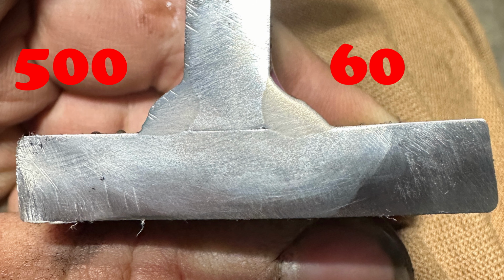Now, as far as root penetration goes, it's a little bit difficult to see, but they're basically identical. A lot of what you're seeing where that rounded edge of the upright plate is, where it looks like a lack of fusion, it really isn't. It's just that I didn't mill flat that edge. And because it wasn't milled flat, there's going to be a little bit of inconsistency weld to weld there. But realistically, in person looking at these, they look very, very similar. And if I did 20 more of them, they're all going to vary about by this much.